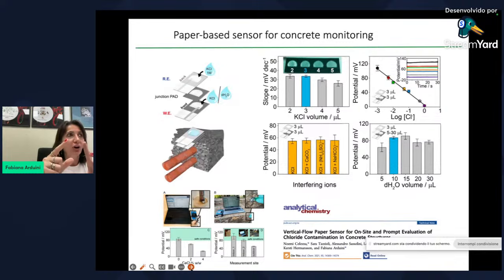In the case of chloride content, actually the only system is invasive because they need to take some sample of concrete to the lab, treat the sample, and use the laboratory instrument setup method. In this case, we again use paper to solve this issue, to measure the chloride on the surface of the concrete structure by using a potentiometric device in which we preloaded a salt solution or KCl in the first layer, working as a reference.